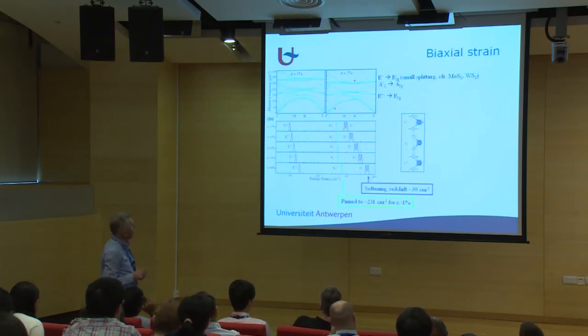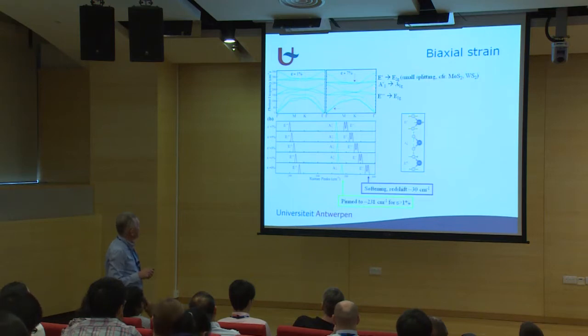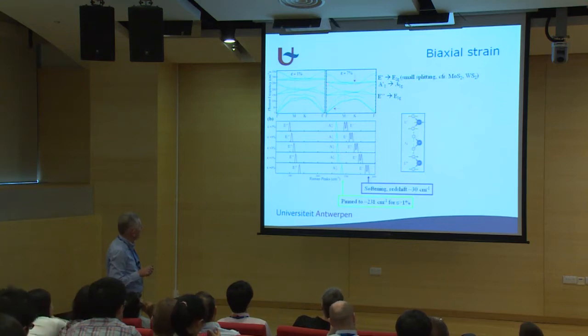And this also agrees with what we found theoretically. This here is the phonon spectrum. If you apply strain, you see indeed that this mode here goes down, and also this one goes down, while the A mode here gets stuck at the same frequency. So that seems to agree with experiment.